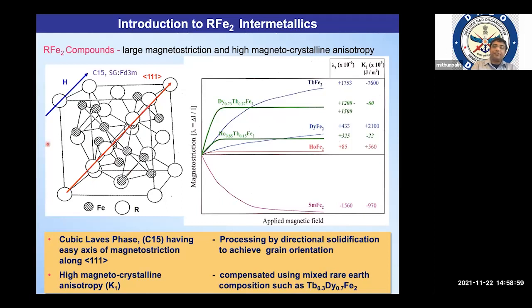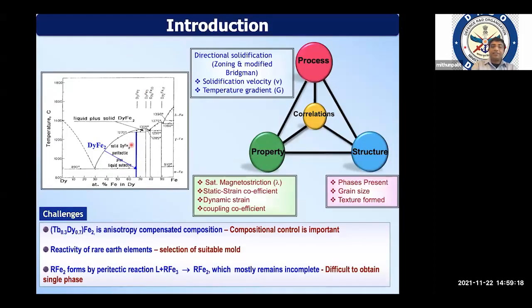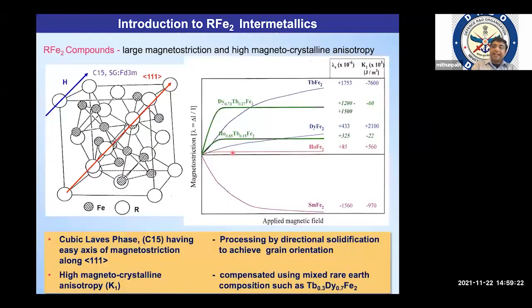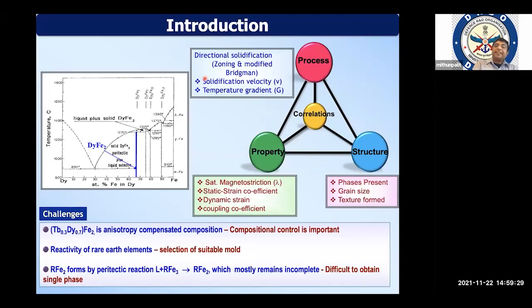This particular material is formed in a cubic structure with 111 as the easy axis of magnetization. So that means the material needs to be, or is preferred to be, oriented along this easy axis so that we can derive the maximum benefit of magnetostriction out of this material. And this material processing is quite challenging. As I was telling, that orientation is mandatory. Therefore, we have to impart some processing route such as unidirectional solidification to make the material oriented along the desired direction. So it is quite challenging in the processing, and moreover, it contains a huge amount of rare earth, and rare earth is very reactive to the environment. So you have to handle the material very carefully under inert condition.